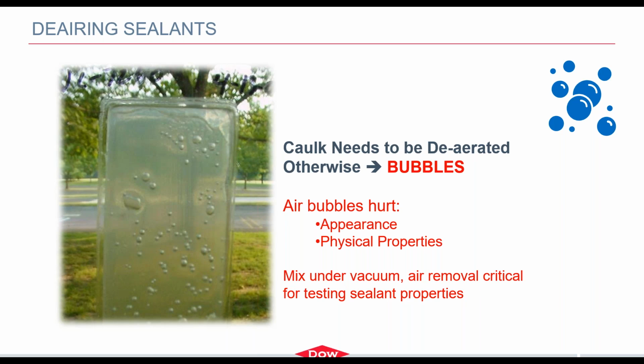De-airing sealants. Now this is key to formulation, and especially when testing performance properties, and is also key for real world application. So sealants are, like I said earlier, formulated at low viscosity, and then they are thickened towards the end once all the raw materials are incorporated in. So by the time it gets to this thickened state, there's air entrapped in your sealant. These sealants need to be de-aired, preferably while mixing under vacuum, because as you can see here, since this is a translucent film, you can actually see all the air bubbles.